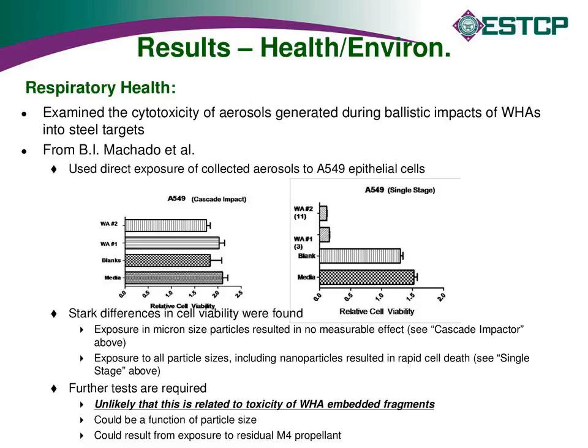So I guess all of this stuff has been published, so I could make the manuscripts available. With Professor Murr at the University of Texas at El Paso, we did some tests where we examined the cytotoxicity of aerosols generated from the ballistic impact, sampled the size of the particles, and there was a fairly dramatic effect, but I'm not sure that was exactly the best screening method, because it could have been altered by the presence of some of the propellants in the test.